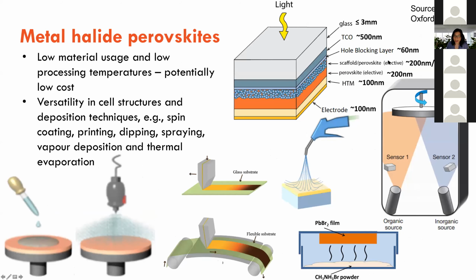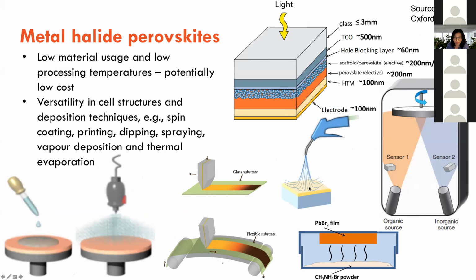So again, I have talked about that you can spray it, you can print it, you can just blow it, by just putting a blob on your substrate and blowing it. You can evaporate it as well. So you can have the perovskite powder, and you can heat it up and it will deposit onto the substrate that you want. And again, it's not very high temperature. We're talking about hundreds of degrees instead of thousands of degrees.